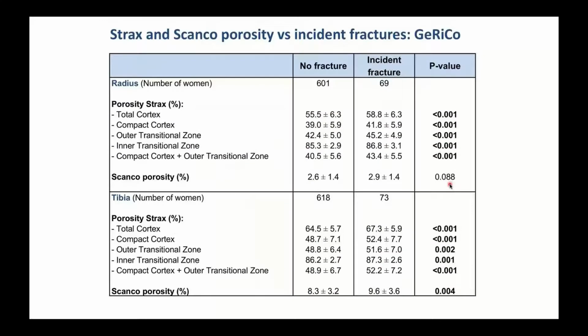And I show you this in our Geneva cohort. This is the porosity at the radius found by SCANCO in our patients without fractures or with fractures, 2.6, 2.9%. This is the porosity that is calculated by the StrAx algorithm. It's in the range of 50%. And so interestingly, whereas the SCANCO may lack sensitivity and does not find a significant difference between fractures and no fractures, the StrAx technique is much more sensitive because it analyzes much larger pore volumes, and then it results in a difference between fractured and non-fractured.